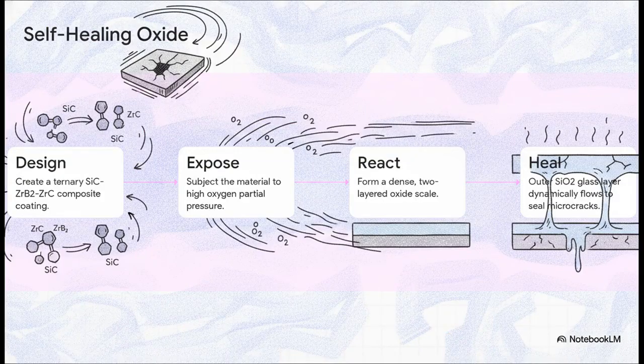But the solution material scientists have engineered is incredibly elegant. Instead of using pure ZrC, they create a ternary composite coating, mixing it with silicon carbide and zirconium diboride. So when this composite gets attacked by oxygen at high speeds, it doesn't flake apart. Instead, it reacts to form a dense, two-layered oxide scale. And the absolute genius of this is the outer layer of silicon dioxide glass. At extreme temperatures, this glass actually flows like a thick syrup, actively seeping into and sealing microcracks the moment they form. It's a heat shield that literally heals its own wounds in real time.